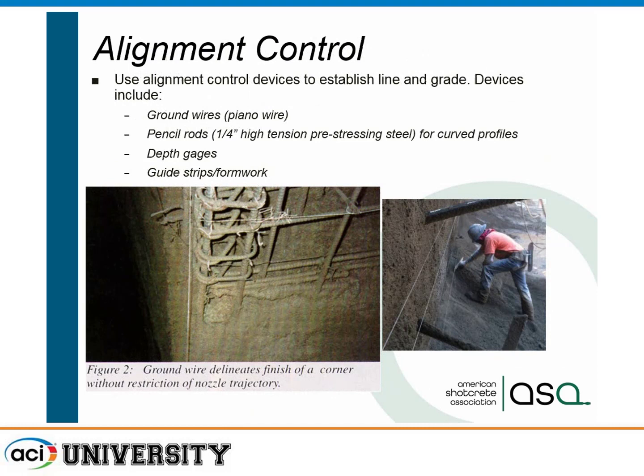How do we control thickness? I mean, we're shooting it and it's coming out of that nozzle. We actually use what we call alignment wires, ground wires, shooting wires. Here, this is the horizontal, so they can make a radius here at the bottom. But the engineer, the inspector can come up and say, okay, I need 2 inches of cover here, so you shoot to it, just a little bit past it, you finish it right to the wire, and you know you have that 2 inches of cover. It also helps us define some of the more unusual curves and radiuses.